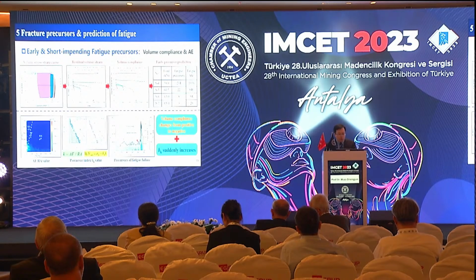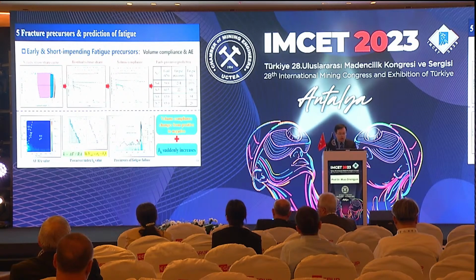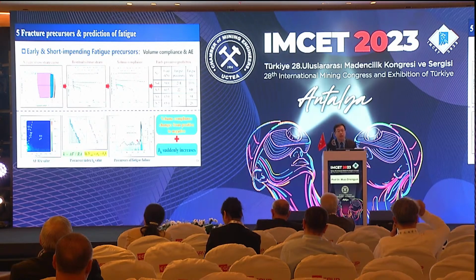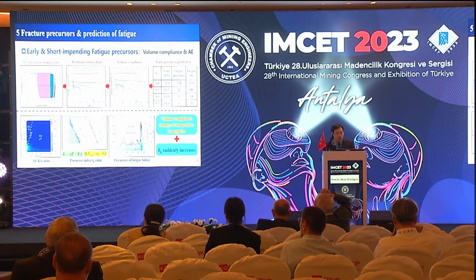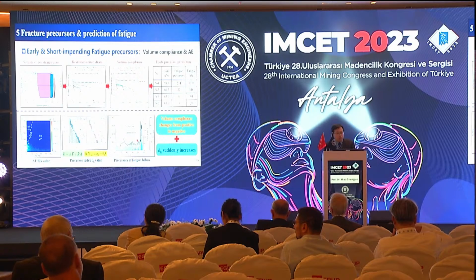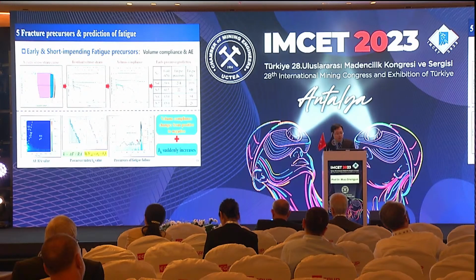Next, we studied the crack growth mode of rock with the AF to RA ratio of AE. We found that it fits a logarithmic linear relationship between the magnitude and frequency of the AF to RA ratio. And the slope decay of this relationship can be used to express the propagation of shear cracks. We also found a significant sudden increase in the b-value prior to fatigue failure occurrence. Therefore, we consider the phenomenon as the short-term precursor of fatigue failure. This indicator can be used to determine when the rock will fail.